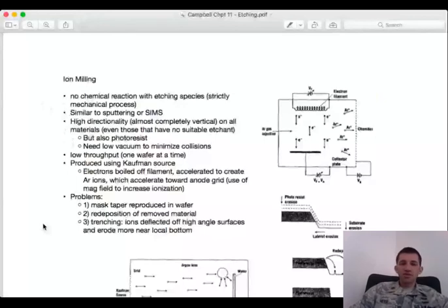They're going in all directions, and some of the time I could be deflecting the ions straight downward, in which case they're going to be funneled into the region that's directly beside this high aspect ratio photoresist, and I might be milling a trench. And so there are unintended consequences of using ions relative to the chemistry. So you get the anisotropy, you lose the selectivity, but you can come with some of these problems. So not every process is perfect.